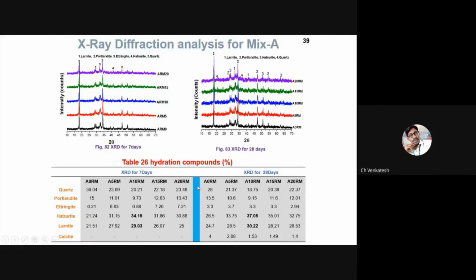So here, I have found that at the 10% replacement, I have observed a higher percentage of Larnite and Hatrurite. So this may be the reason for developing high strength at a 10% replacement level of red mud. As I told you earlier in the mechanical properties, I have found that 10% replacement has high compressive strength, high split tensile strength, and high flexural strength. The reason may be the presence of a higher percentage of Larnite and Hatrurite at the 10% replacement level.